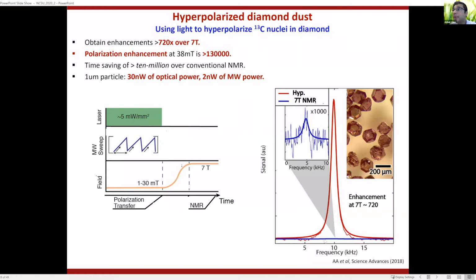Here are some typical results from some particles. So this blue line is an NMR signal from about 1 milligram of diamond, and that's a very weak signal. That's at 7 Tesla. I think a few hours of averaging gives you that kind of SNR. And a few seconds of optical pumping can give you that kind of signal to noise. So the spins are very highly polarized.